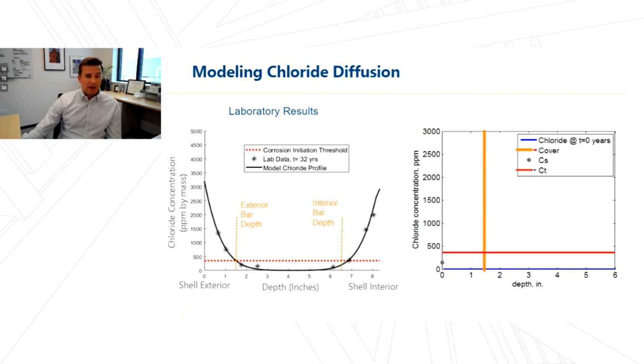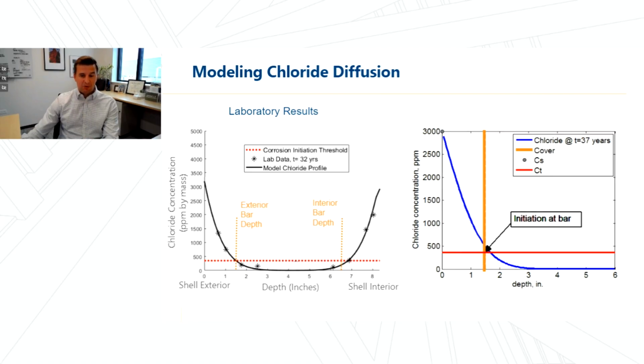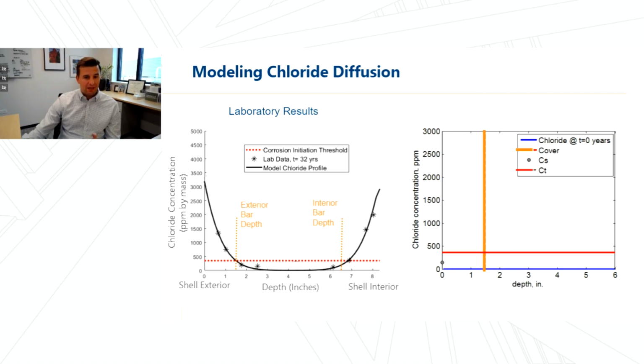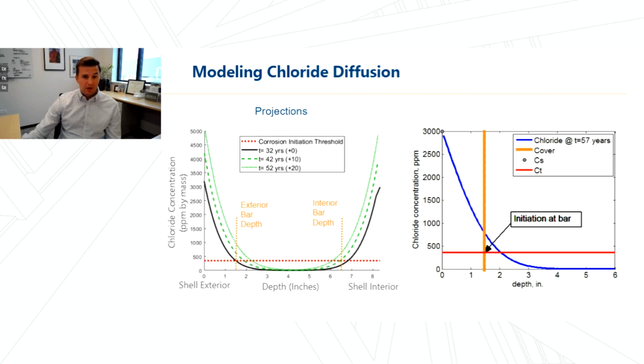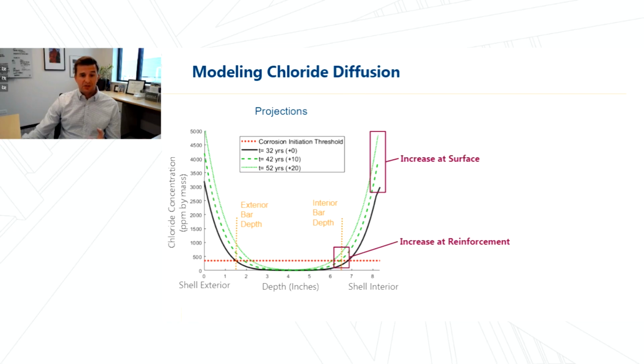But we do have means to model this diffusion over time. I should note that this animation is not from this example project, but it still illustrates the point that we can model diffusion and we can calibrate that model of diffusion to the specific structure that we're analyzing. When we do so, that allows us to predict over time the increase in chloride concentration, the change in this chloride profile over time. That's what we see with these green lines, projecting out 10 years and 20 years from our measured data point represented by the black line. We'll note 2 things about this. One is that there's an increase in chloride concentrations at the surface.